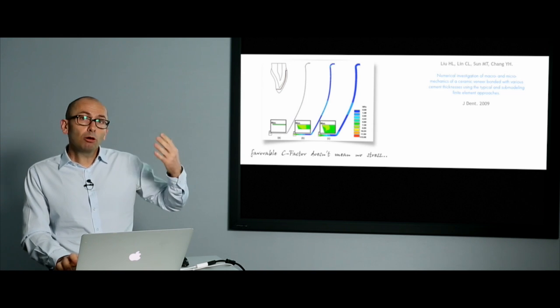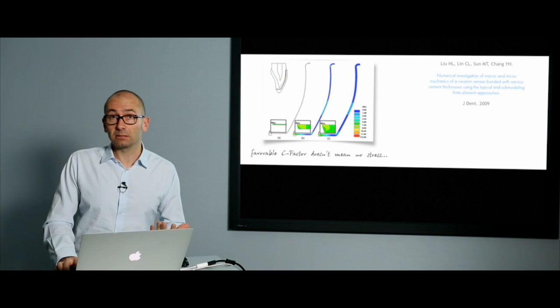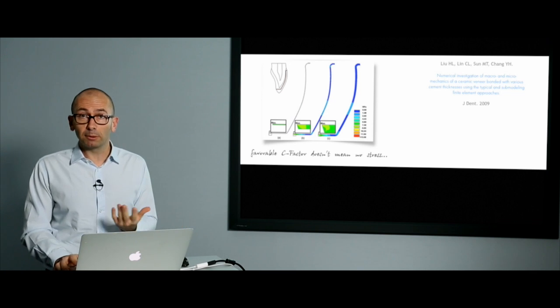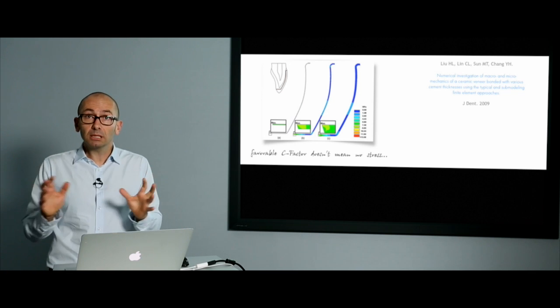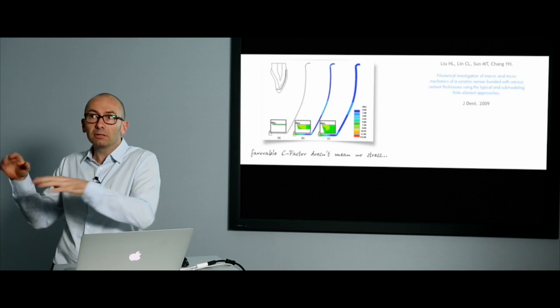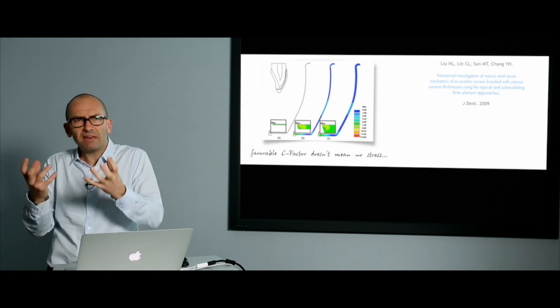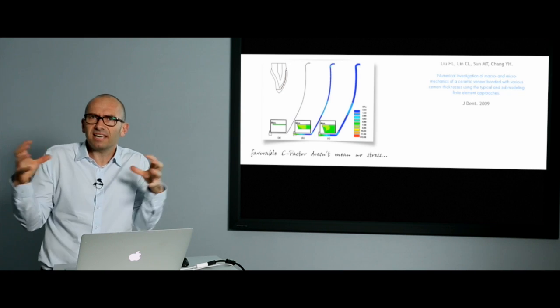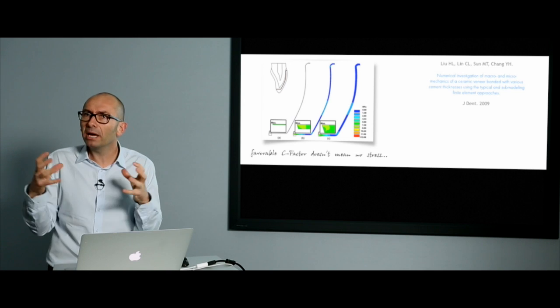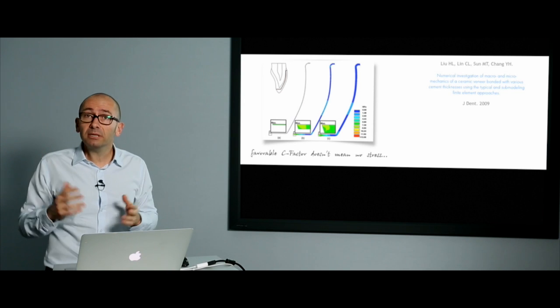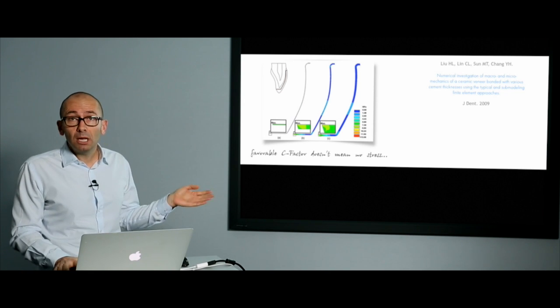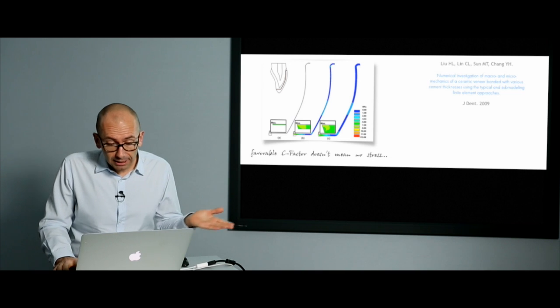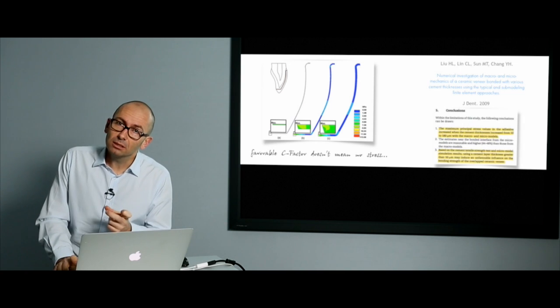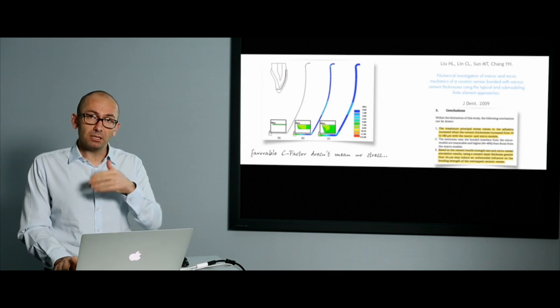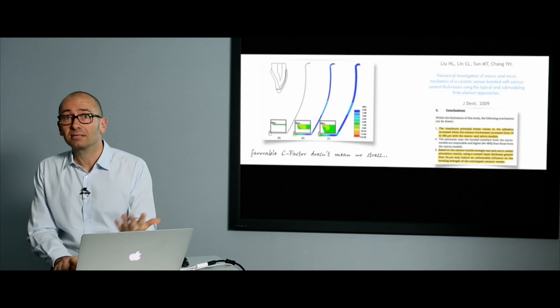because we think, and we are wrong, I think that speaking about veneers, you don't have any problem with the C factor, the configuration factor of the preparation, because it's more or less flat. So you see, it's not like at the posterior, when you've got complex cavities and complex C factors and tension and stress everywhere with the shrinkage. At the anterior, there is not a problem. It's true, but just remember that when the thickness of the luting cement is increasing, the stress is increasing.